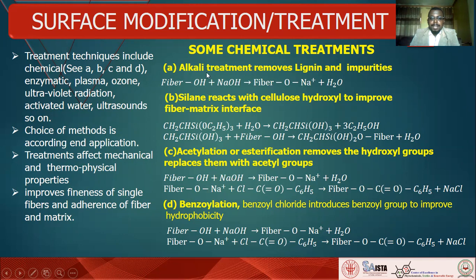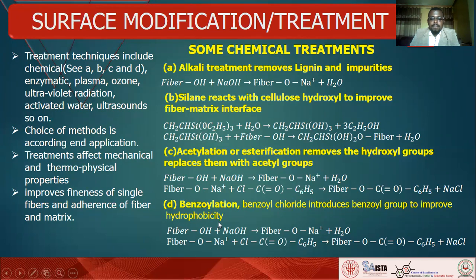For example, alkali treatment could be combined with some of these methods to get better results — perhaps improving fineness or adherence between fiber and matrix. Some other chemical treatments include silane, acetylation, esterification, or benzoylation. Some of them help to maximize hydrophobicity.